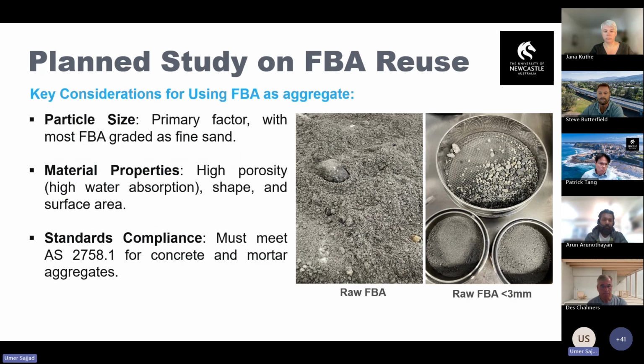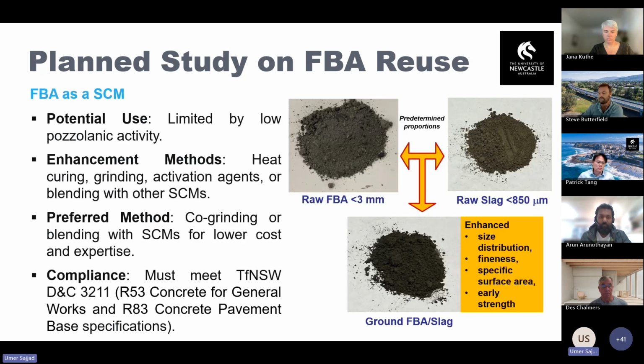But how are we using the furnace bottom ash, and what are the major parameters? First of all is the particle size. As said, it is slightly coarser than fly ash and normal supplementary cementitious materials. So that's why it is feasible to use it as fine aggregate as well. It has high porosity, high water absorption, and the shape and surface area is slightly higher compared to the natural sands. But it meets the compliance of AS 2758.1, in which we have compared the characteristics of furnace bottom ash with the aggregates which can be used in concrete and mortar, and it lies within those ranges.